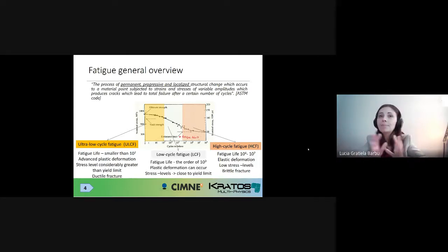Now, in the middle, we have this gray shady area, which I will call low cycle fatigue. The lines are in between the two poles that I mentioned. So let's say about thousands of cycles, tens of thousands of cycles, hundreds of thousands of cycles. We can have plastic deformation, of course, at several different levels. And the stress levels are close to the yield limit when we are closer to the high cycle domain, and they progressively increase as we get closer to the ultra-low cycle fatigue domain.